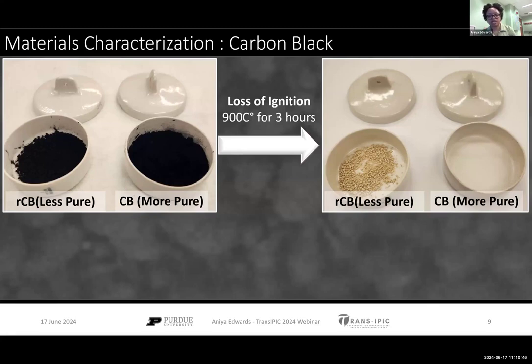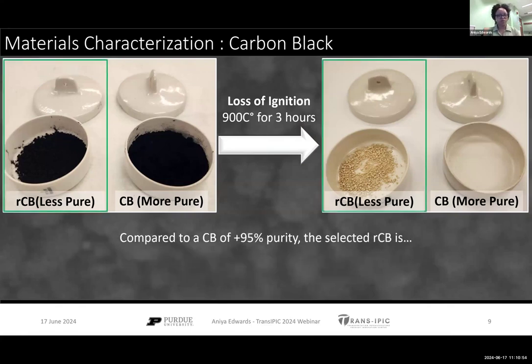After doing some XRF testing, we found that it was sulfur and other inorganic compounds, but that kind of proves just how impure it actually is. However, we still decided to go with the recycled carbon black for our mixes because compared to the pure carbon black, which is about 95% purity, the recycled carbon black is less expensive and it's more environmentally friendly. So we're really trying to affirm that environmental sustainability aspect.